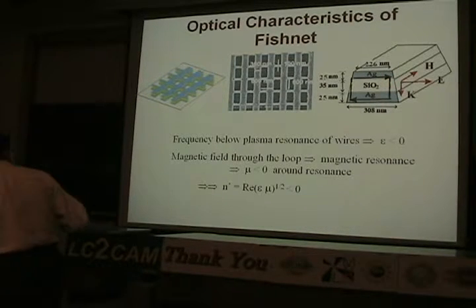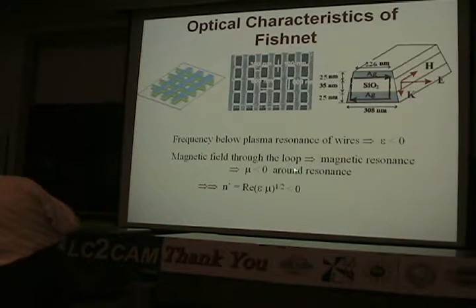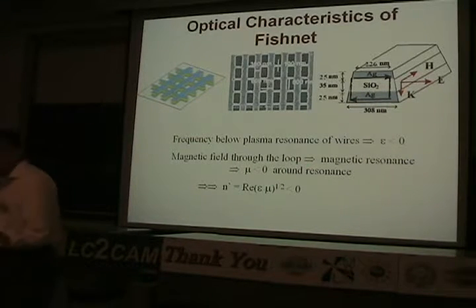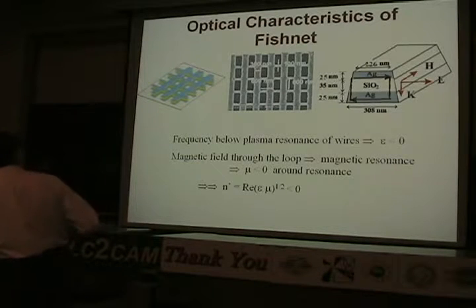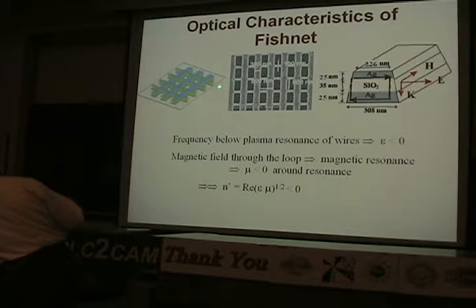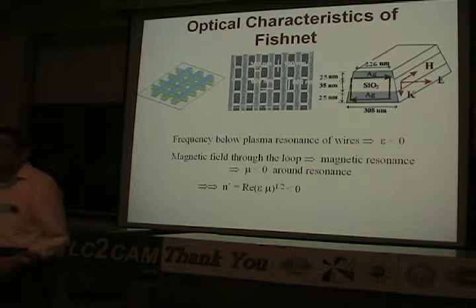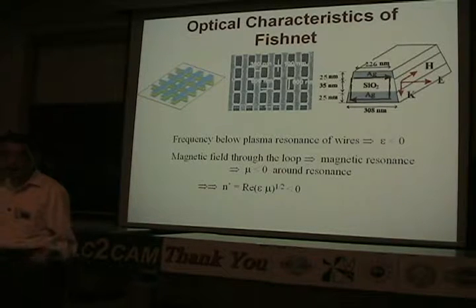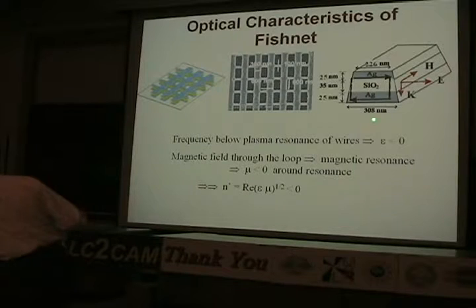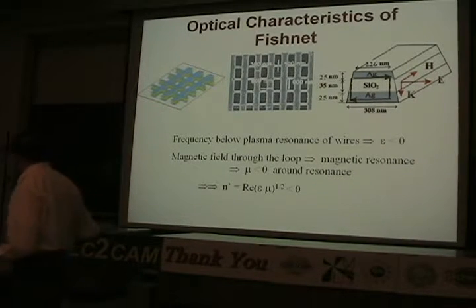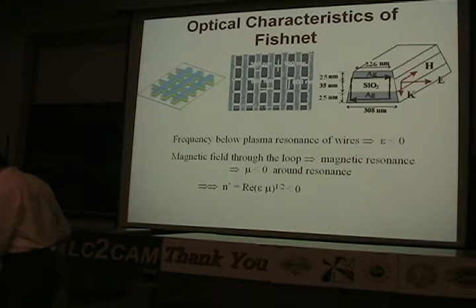And on the other hand, this magnetic resonance will give you mu less than 0 at a slightly higher side of the magnetic resonance. And then you also have the field linking these wires, and the electric field is parallel to these wires. That will give you the plasma response. So in that case, epsilon less than 0, and that gives you n less than 0. So what do you get?